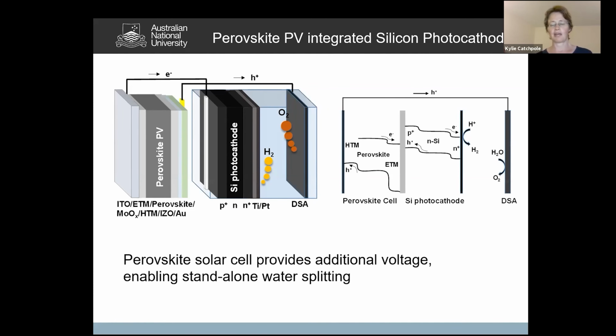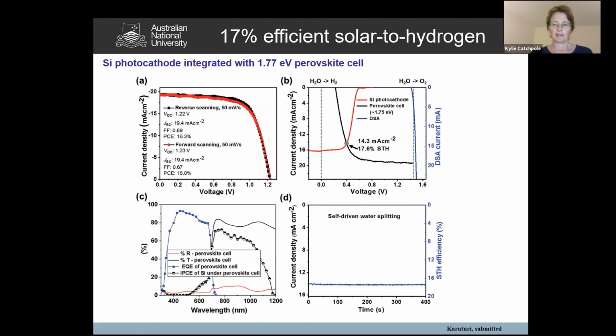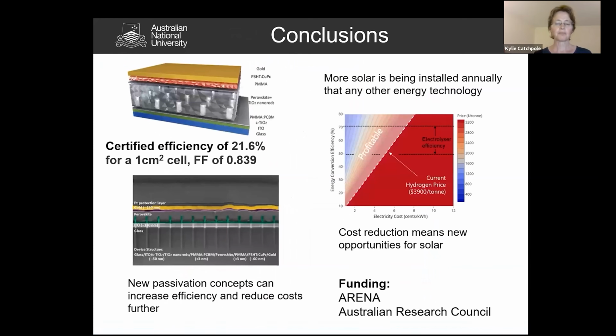Always with these situations, you have an overpotential. So the voltage that you have from the tandem is actually very well matched to the voltage that is required in practice for water splitting. So this shows you results. We integrated a silicon photocathode with a perovskite cell, and overall we're able to get an efficiency of 17% for solar to hydrogen generation using that combination of the perovskite and the silicon photocathode.